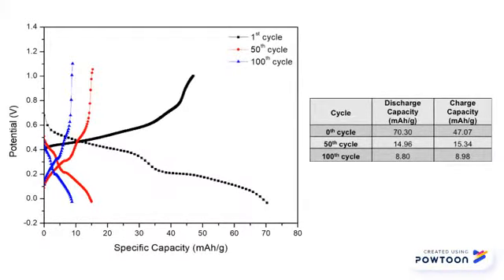For the charge-discharge analysis, high initial charge capacity and discharge capacity can be seen from the table. The capacity also decreases as the cycle increases. That matches the results of the CV and EIS. In the previous work, charge capacity is 45 mAh per gram and discharge capacity is 70 mAh per gram in a whole battery system. But in our case, it is only a half cell system, so our reading is relatively high compared to the previous work.